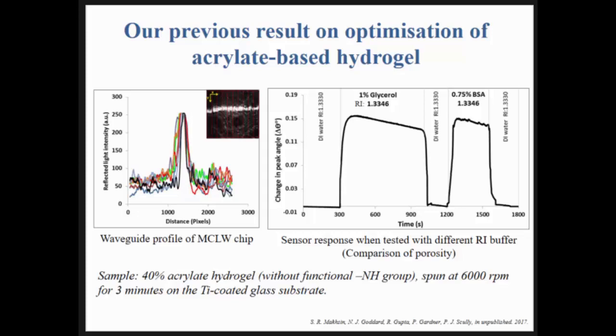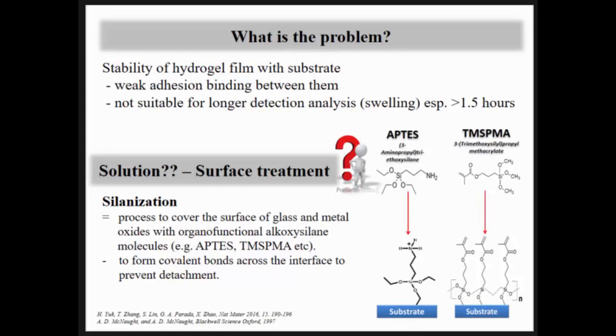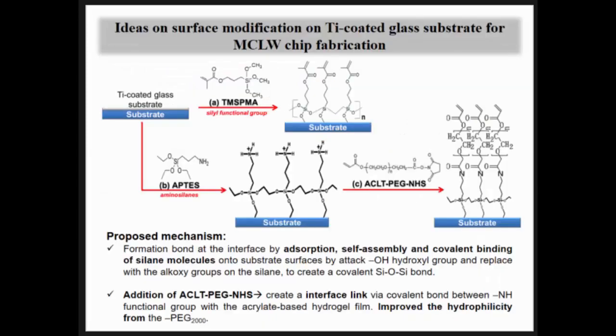However, the problem occurs when we try to prolong the detection to more than 1.5 hours, because we try to immobilize the protein for the bacteria. We found that the hydrogel easily detaches from the substrates. One solution is the silanization process, a process to cover the glass or the substrates with an organofunctional group so that it can provide covalent bonding between the substrates and the hydrogel. The idea came when we wanted to try a few types of chemicals commonly used for this process, because it can provide the Si-O-Si group here, same with this too.